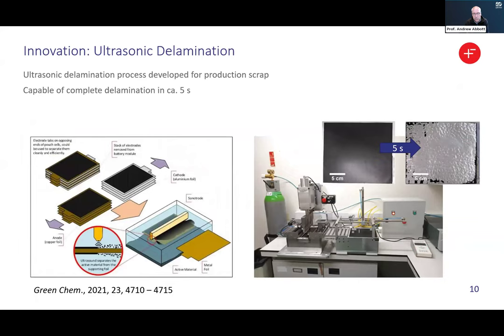So one of the innovations that we've put into our processes is to use ultrasonic delamination of electrodes, and this works particularly well for production scrap. So we take the electrodes and we pass them under an ultrasonic horn, and this is a small demonstration unit that we've got in our labs in Leicester, where we have an automatic suction device that picks up the electrodes, puts them onto a conveyor belt, and those are then fed underneath the ultrasonic horn and give us our pure current collectors within about 5 seconds. So we can take a 20 centimeter typical electrode and delaminate it in around about 5 seconds.